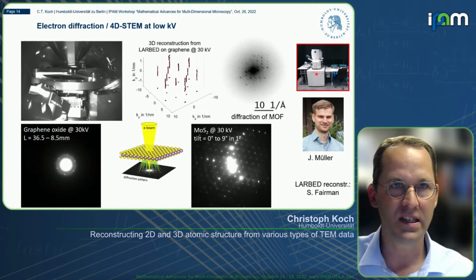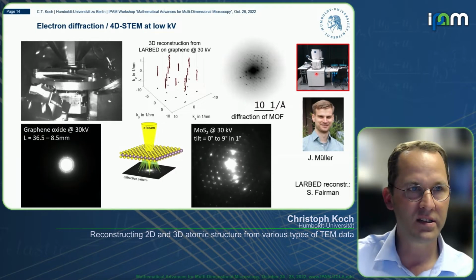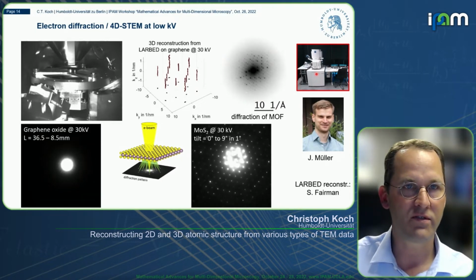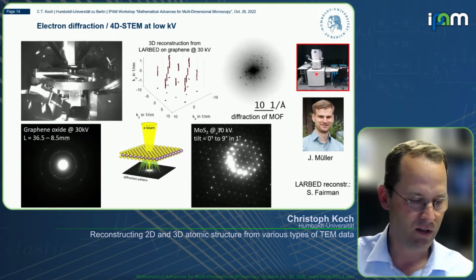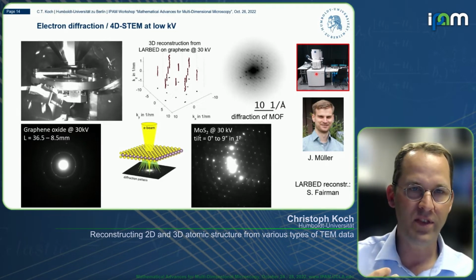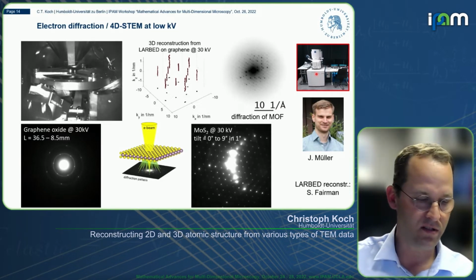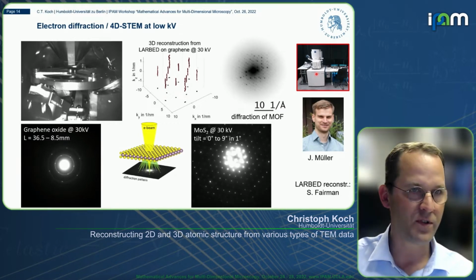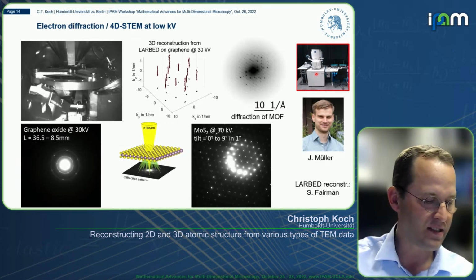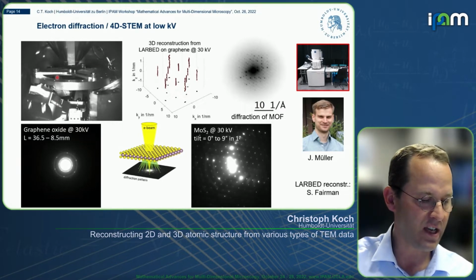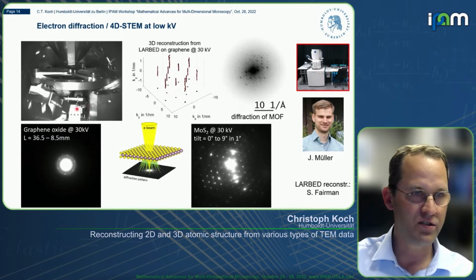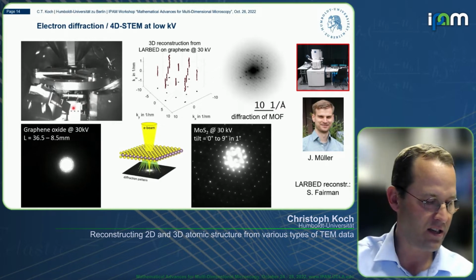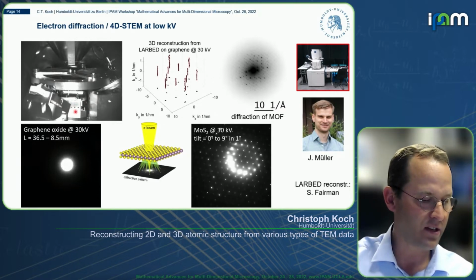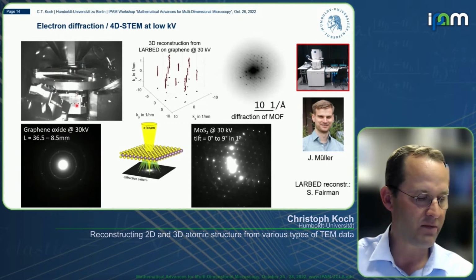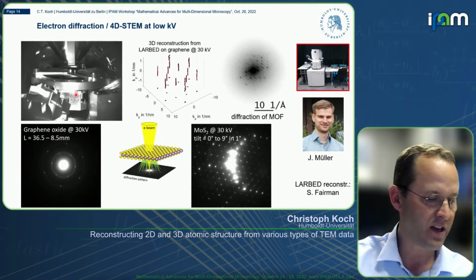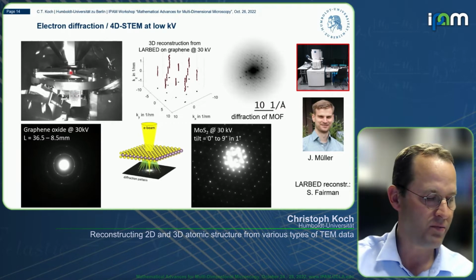So this is just an SEM. It's not intended to be a TEM. It's not made as stable, but we're working on that to actually get also atomic resolution from it. I cannot show that yet to you, but even without going to atomic resolution, you can still do a lot with these instruments. For example, because you have so much space inside, you can build special diffraction stages where you can have a camera that you put in yourself, and this can also physically change the camera length. You can see now the camera length is shortened because the camera is moved closer to the sample, and the sample sits right here, and the electron beam comes through this pole piece right here.